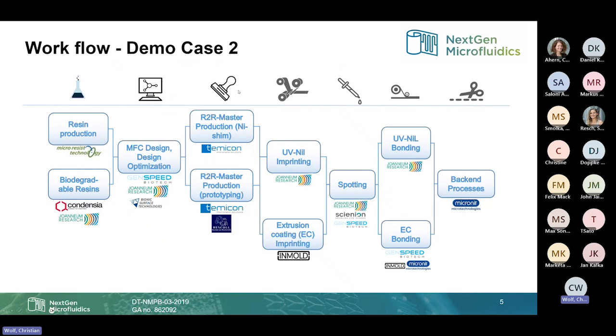You also need a roll-to-roll master production, or as we call it in the roll-to-roll language, shim. So these are the stamps which are wrapped around the actual cylinders, which press the structures into your resin film. The next step is the actual imprinting. You've already seen the animation of the UV-NIL imprinting process, but in our project we also developed a second, quite similar process called extrusion coating. I will show that in a little bit more detail later on.